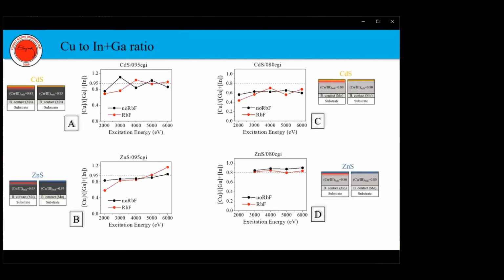After applying the necessary normalization procedure to recorded data, we calculated some elemental ratios for all samples and compared them. In this slide, I present the copper to indium plus gallium ratio. The dashed lines in this graph represent the nominal bulk values. It is a known property of CIGS solar cells that the absorber presents a pronounced copper poor surface. This can be seen in the copper poor sample in figure C. The relative copper concentration there lies well below the bulk value.